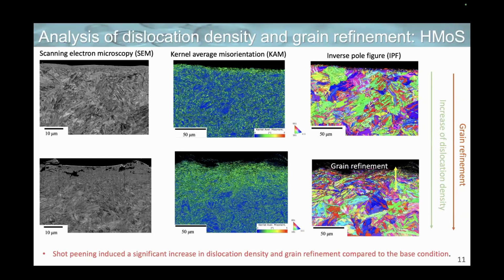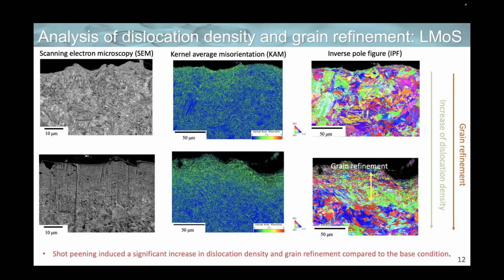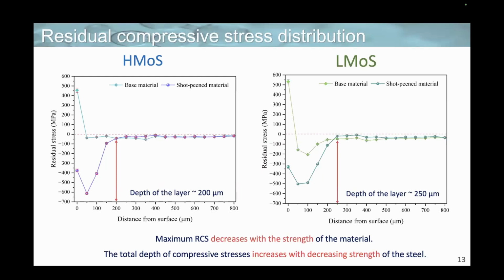Then we wanted to confirm the effect of plastic deformation, and for this purpose, we did analysis of dislocation density and grain refinement. In the first row, you can see the results of a material in the base condition, and in the second row, you can see the results of a material with the shot peened layer. From the kernel average misorientation maps, we can see that we have a significant increase in dislocation density due to shot peening. And also from IPF images, we can see that we have a significant grain refinement. The similar situation is observable for the low molybdenum steel. Also after shot peening treatment, we have increase in dislocation density and the depth of grain refinement is even more pronounced. So yes, we have an increase in dislocation density and we have a grain refinement.